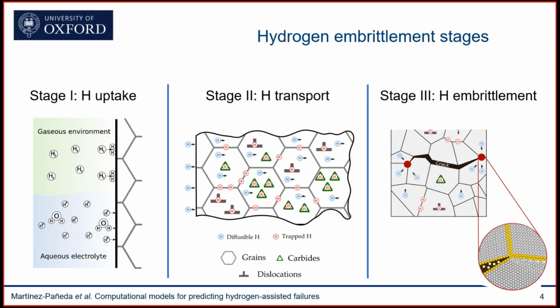What we wanted to do was to propose a physically based model, a mechanistic model. And by this, I mean a model that explicitly resolves all the physical processes involved in hydrogen embrittlement, and that takes as input only physical parameters, material properties that we can independently measure in our lab. So this has always been our objective. Only by being mechanistic, by resolving the physical processes, by taking as input physical parameters, can we be confident that our model is not only able to interpolate between the experimental data points, but it's also able to extrapolate. And this is key in these hydrogen energy applications.